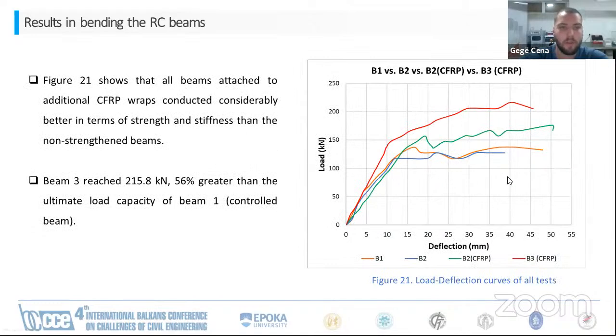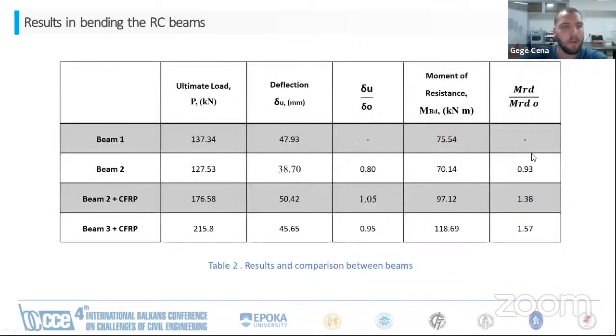Figure 21 shows that all beams attached to additional CFRP wraps performed considerably better in terms of strength and stiffness than the non-strengthened beams. So beam 3 reached 215.8 kilonewtons, that is 56% greater than the ultimate load capacity of beam 1. We can also see the graphic of the cracks, and we can compare the graphic of beam 3 with the graphic of beam 1. These are the results that show that beam 3 is 1.57 times stronger than beam 1.